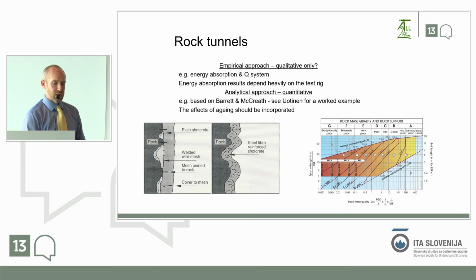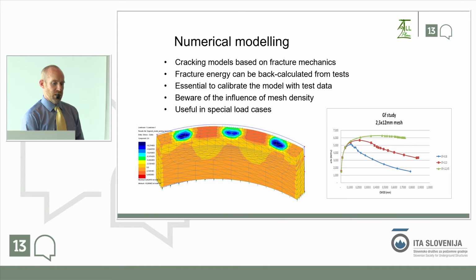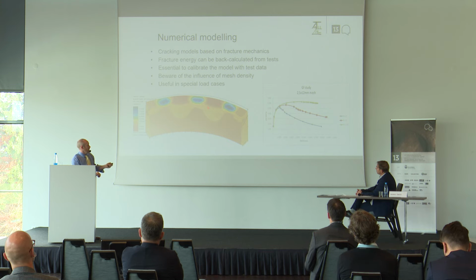Rock tunnels, slightly different. We're generally working off the Q system with any energy absorption, so I'll skip over that, but happy to talk about it later. If you have something quite complicated, here this is some work I did a few years ago looking at segmental linings, so it's a purely fiber reinforced segment for a metro tunnel, and you have the governing load, essentially it's the ram loads as you push the TBM forwards. You get these very high concentrations of compressive strength, and then you get tensile splitting tends to appear in between.